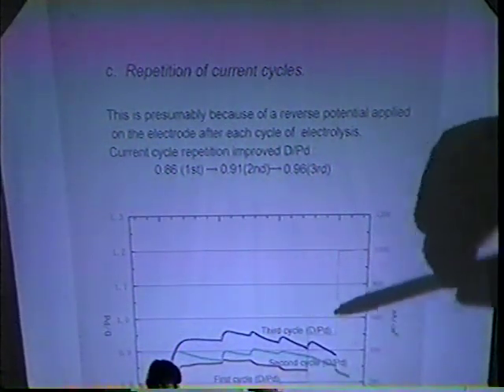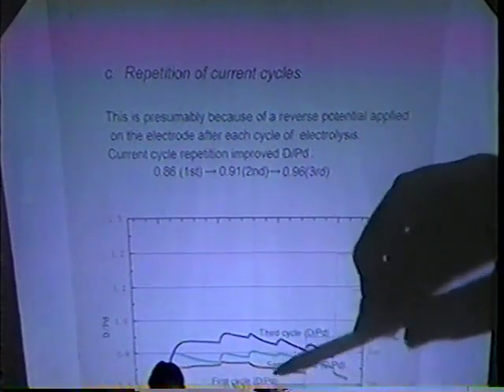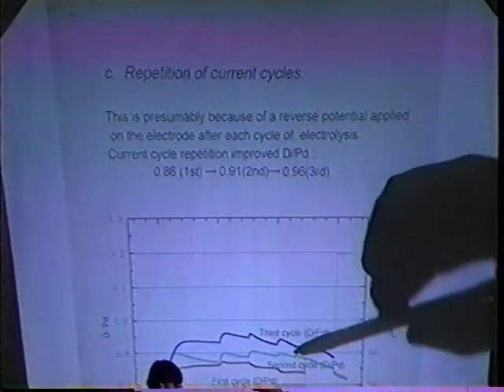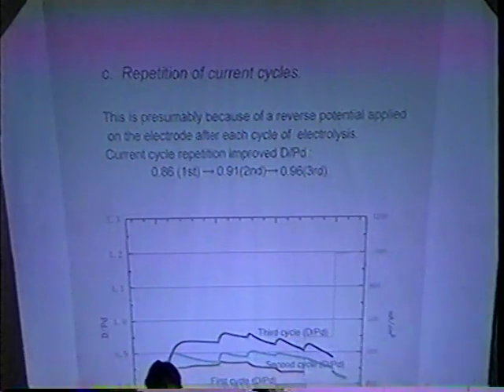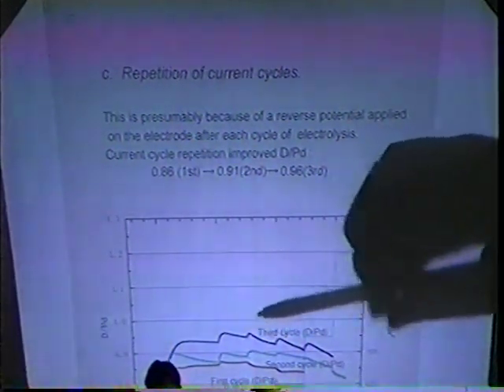This figure shows that there is a beneficial effect in repeating the current cycle a second and third time. The maximum D/Pd ratio in the first cycle is 0.86, lower than that reached in the second, where diffraction is 0.9, and the third cycle, 0.96. With each repetition of the electric cycle, the maximum D/Pd ratio was larger than the D/Pd ratio reached in the previous cycle.